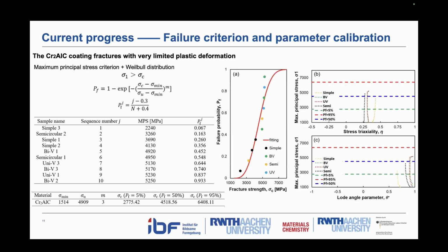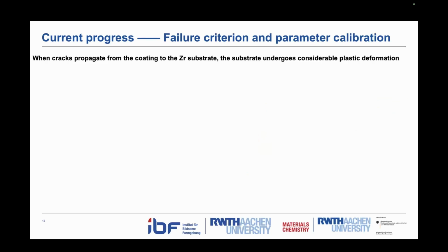So the right side shows the failure probability with the corresponding fracture strength, and also how the maximum principal stress is involved with the stress triaxiality and load angle parameter, and shows we managed to cover a relatively big stress state. So similarly, for the crack propagation from the coating to the substrate, the substrate undergoes considerable plastic deformation according to our simulation results.